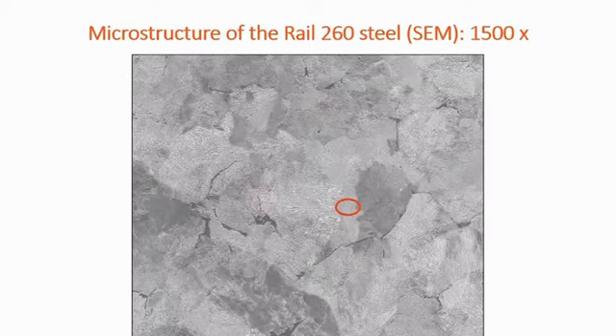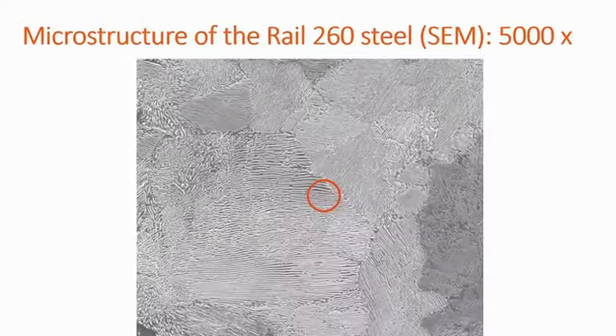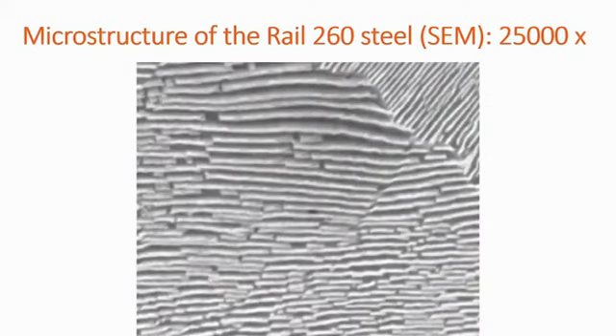When you use a scanning electron microscope to look at the microstructure of pearlite, you have to go to very high magnifications to understand something. This is a metallographic surface etched with Nital, and the ferrite is the one that is consumed, and the cementite is the one that stands out. Here the white platelets are the cementite, but you have to go to 25,000 X to really see something.